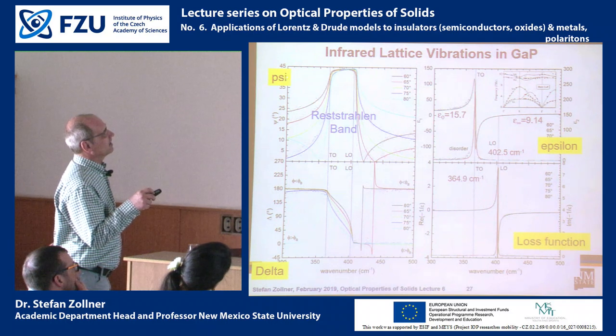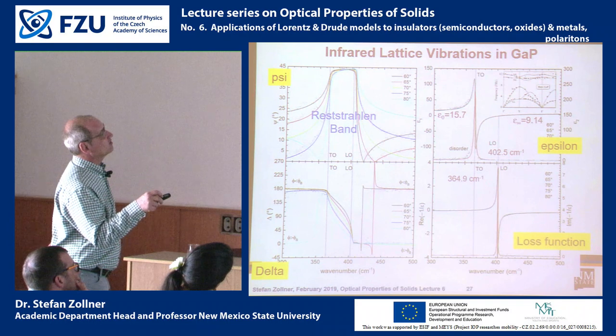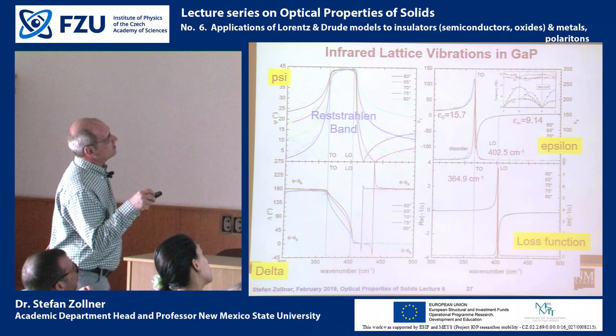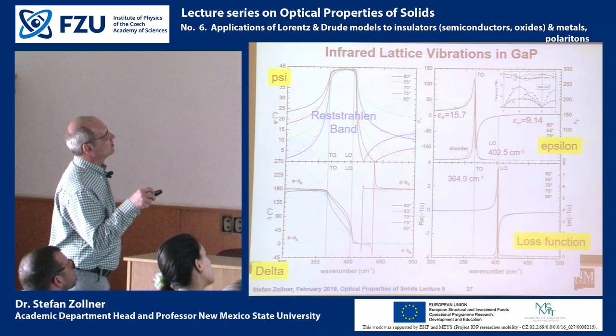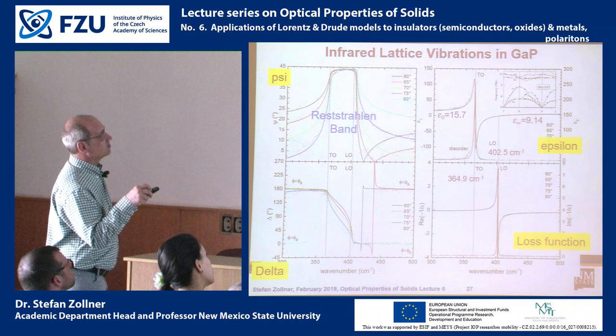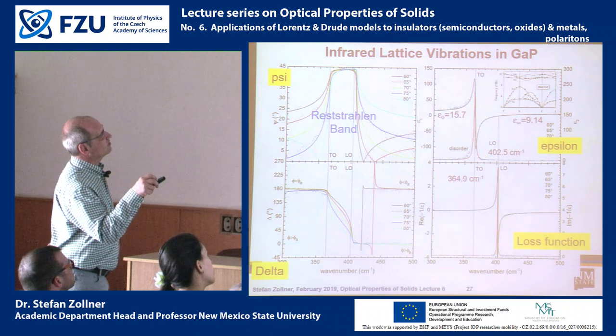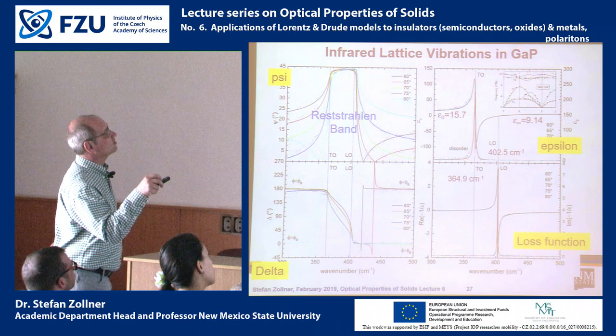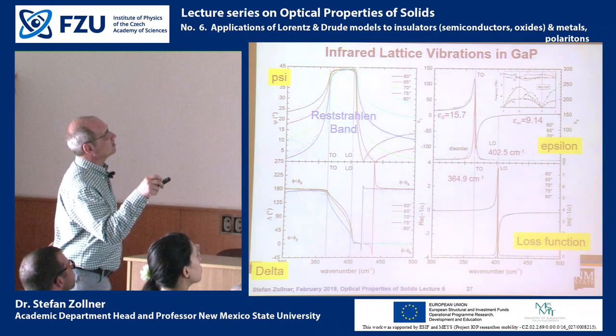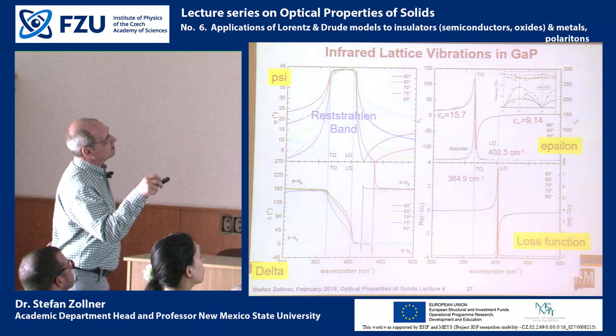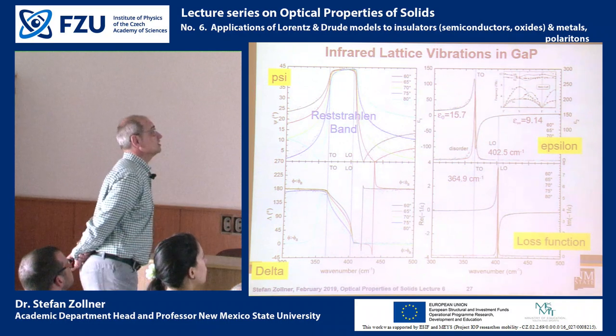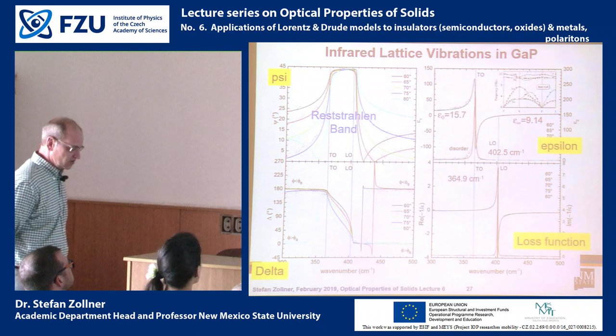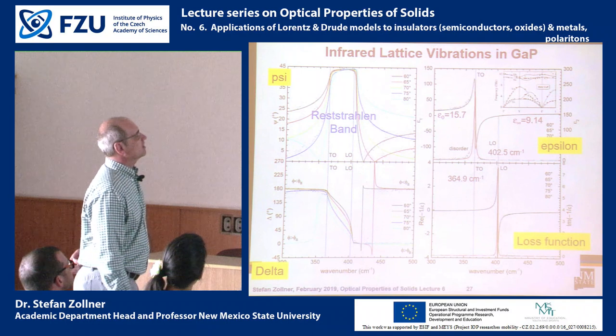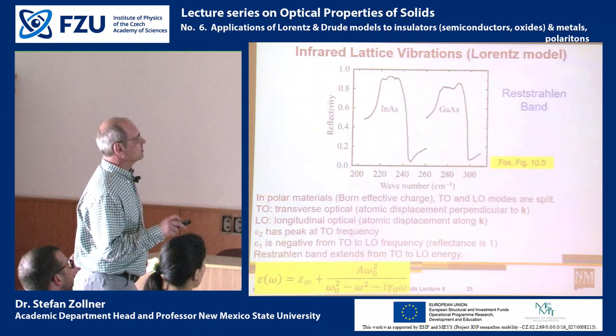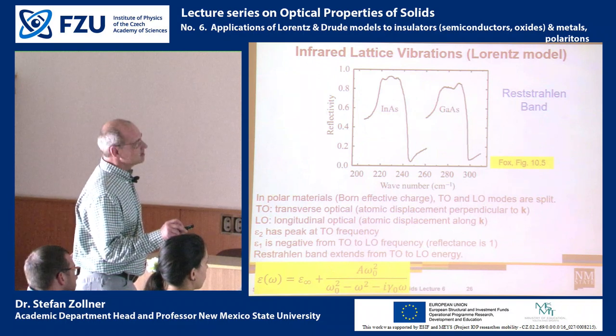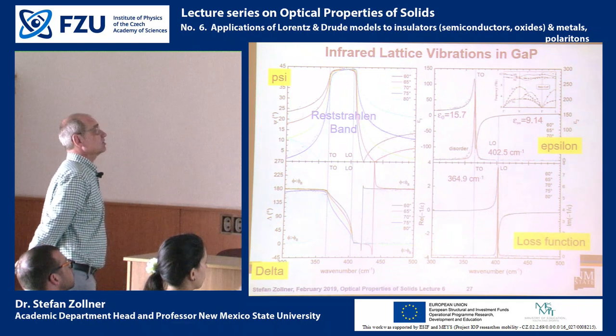So this is the ellipsometric angle psi, which is plotted as a function of wave number for different angles of incidence. And what we see here is, let's take 65 degree angle of incidence. The psi starts at a rather low value, and then it gets close to 45 degrees at the TO frequency, which is shown by the dotted line. And then the psi stays at 45 degrees, and then it drops again. And you see the actual drop is a little bit higher than the LO frequency. So graphically, it is not possible to read the LO frequency from these data, but one needs to model the dielectric function using this Lorentzian oscillator. And here in gallium phosphide, the model works really, really well.